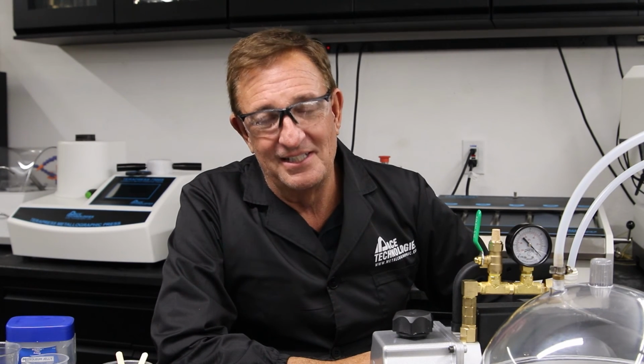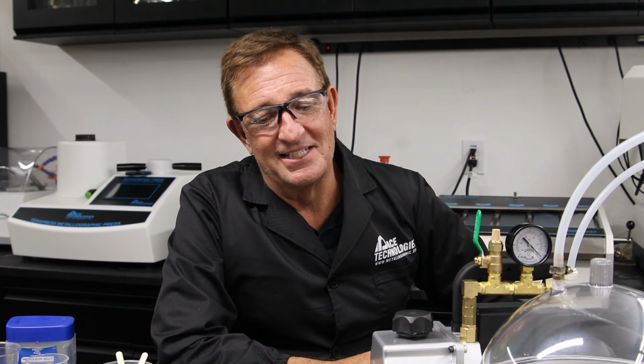It also applies pressure. The nice thing about castable mounting is that you're not putting a lot of pressure on the sample with a powder that may actually crack your sample. So in addition to filling porosity and voids that are in your sample, castable mounting can be very useful for a wide variety of materials.